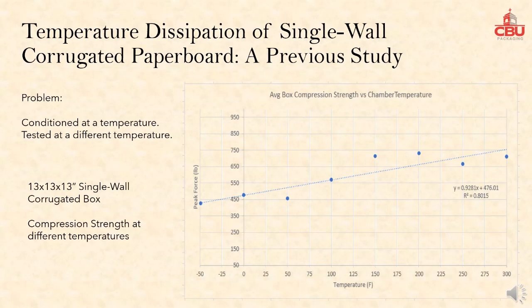From the same recent study, compression strength of corrugated box varies depending on the temperature. For example, if a corrugated box is conditioned at 300 degrees Fahrenheit, but tested at 200 degrees Fahrenheit, the compression strength will be about 93 pounds lower.